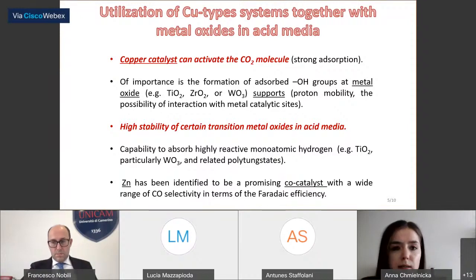So the concept of utilizing a copper-type system together with metal oxide in acid media includes that the copper catalyst can activate the CO2 molecule, the high stability of certain transition metal oxides in acid media, and the capability to absorb highly reactive monoatomic hydrogen. Zinc has been identified as a promising co-catalyst with a wide range of CO selectivity in terms of Faraday efficiency.